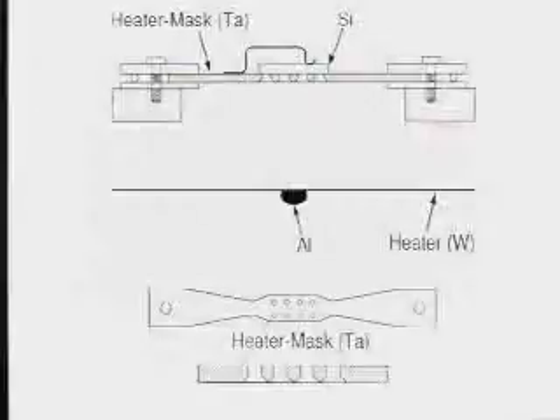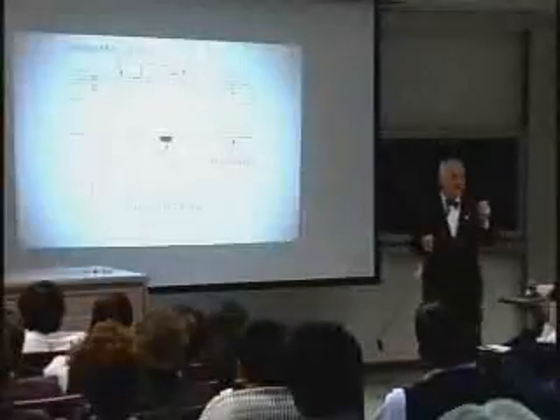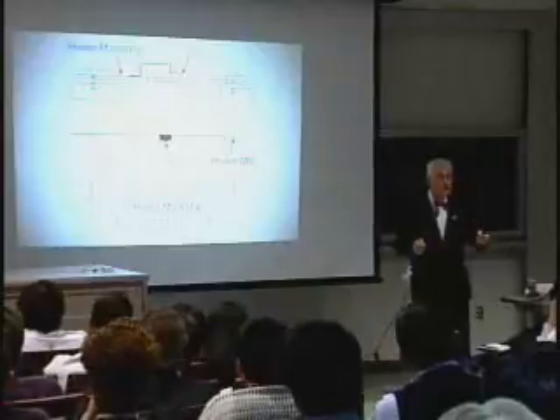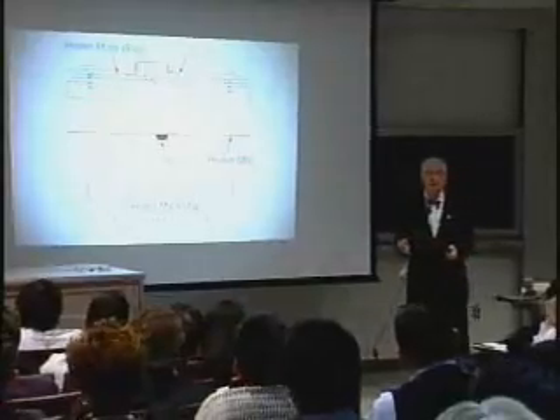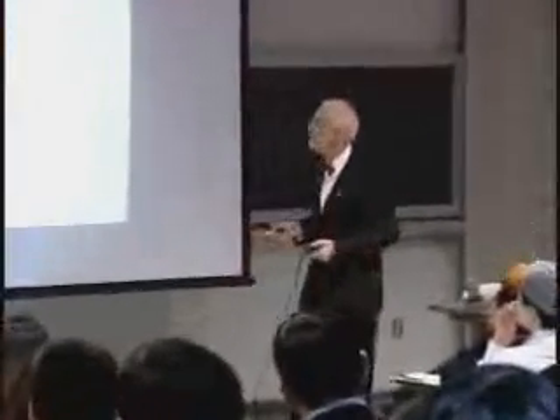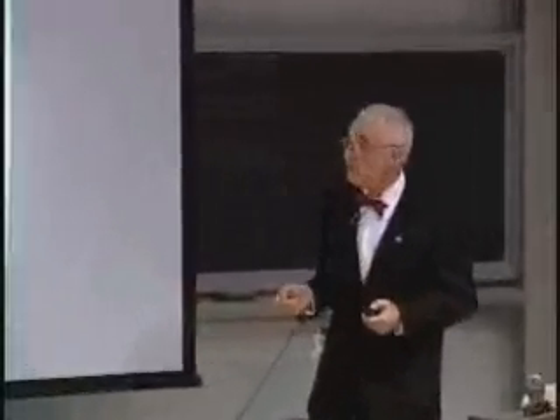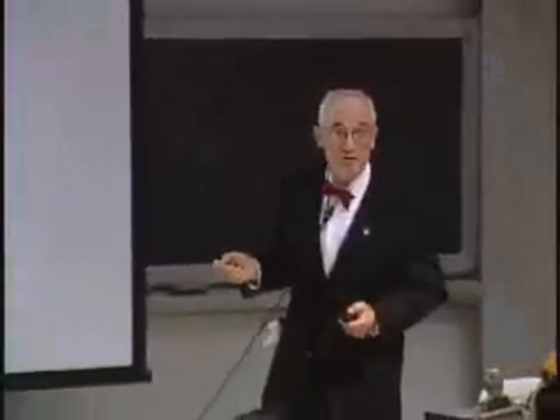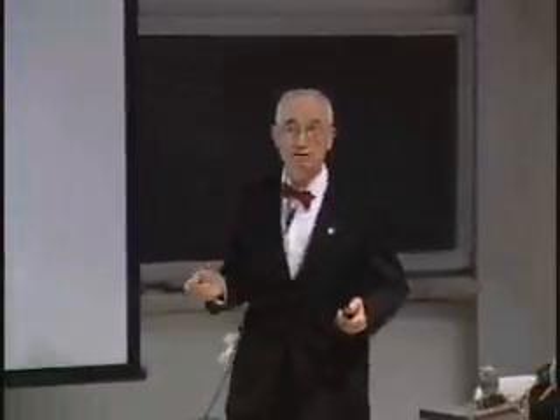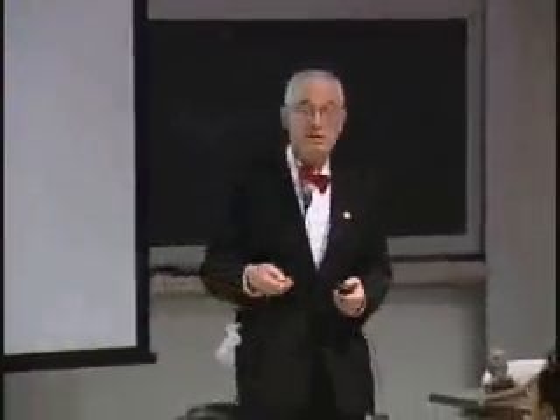And we have a mechanical shutter we can put here so that we can grab off the first oxidized aluminum that we want to get rid of and get to good aluminum before we let it deposit on top of the silicon. And we can deposit it on cold silicon, hot silicon, whatever. Tannenbaum was trying to do this before us and was having troubles trying to get aluminum to stick right on hot silicon, and we solved that problem on what turned out to be his machine. So he has the advantage because he owns the machinery. In other words, we can be dispossessed.